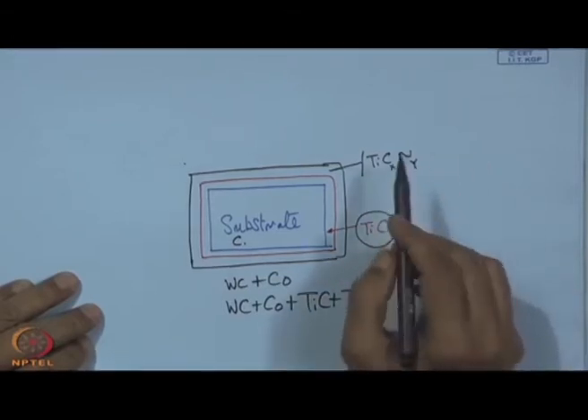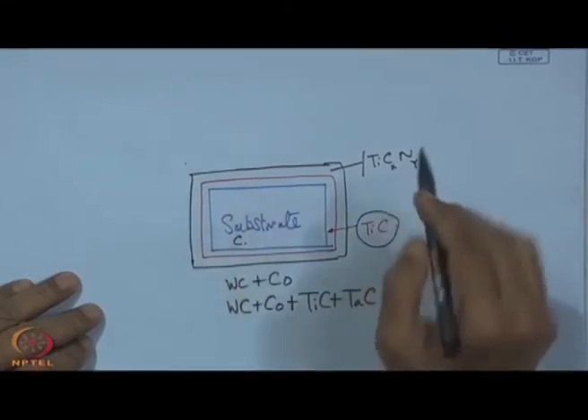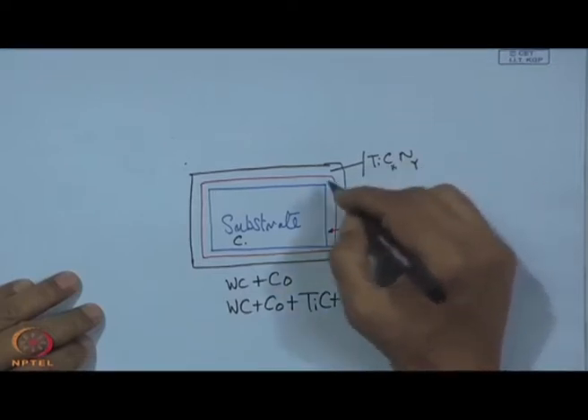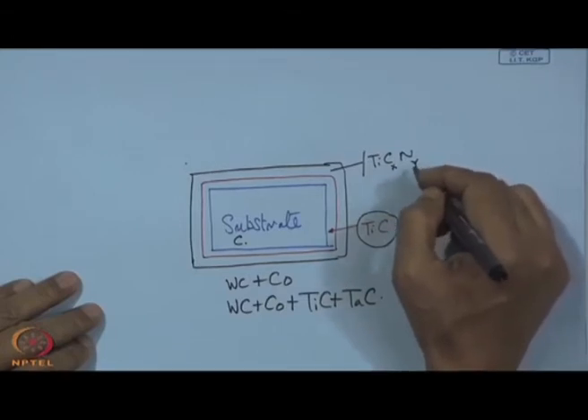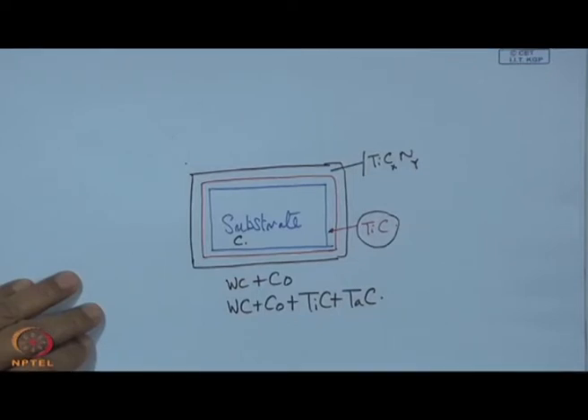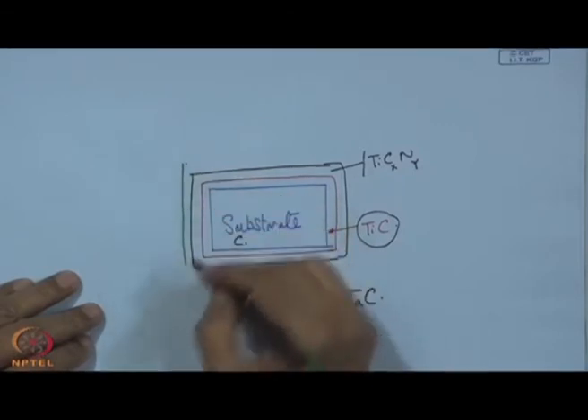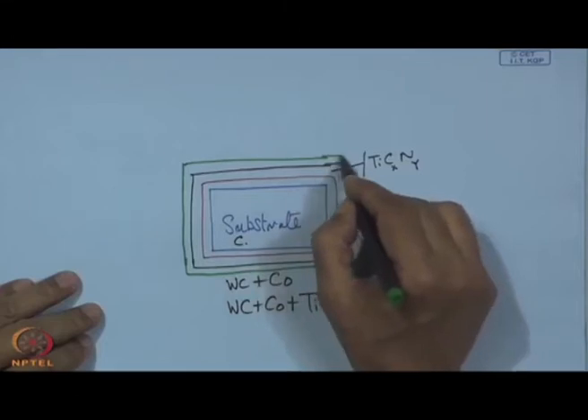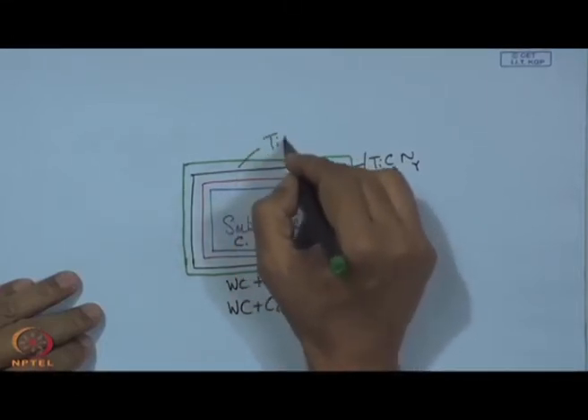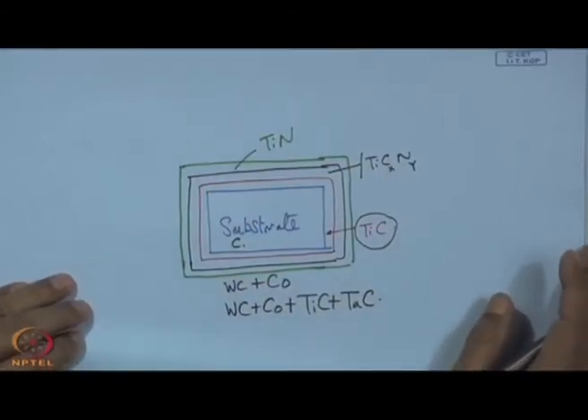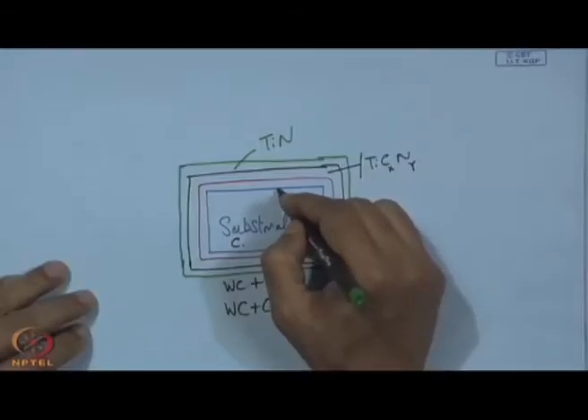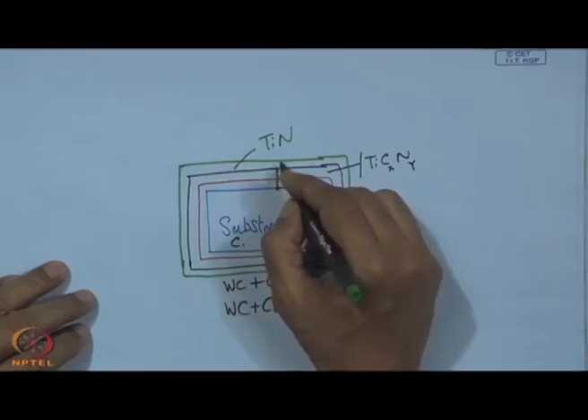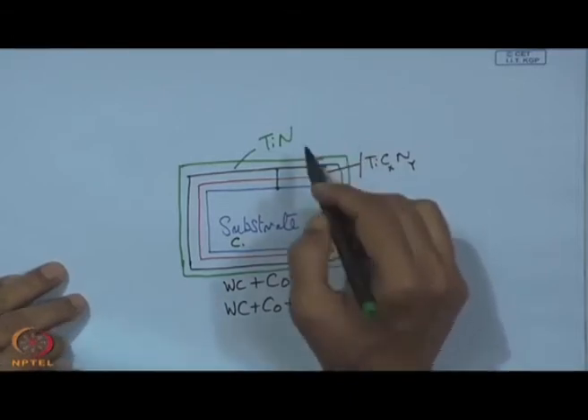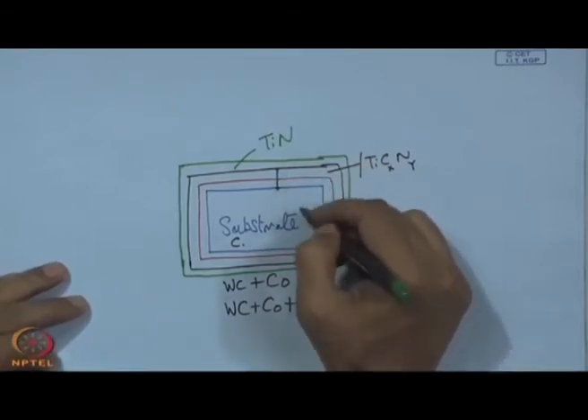So, x and y can be varied, and when it comes to the top of this transition, the value of y may be quite high and x may be small, and at the beginning the x value is high compared to the value of y. So, this transition keeps on going, and finally what we get at the top is this TiN, and this TiN is actually the functional coating. So, though it is CVD of TiN coating, to have an effective high-performing coating, one has to do this preparation starting from the substrate, getting TiC, then the transitional coating, and finally this TiN coating. This way one can get a well adherent, integral coating with this substrate surface.